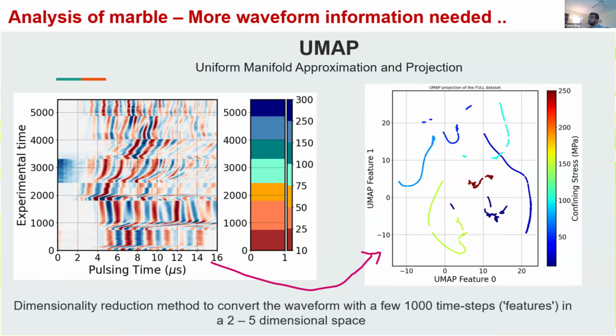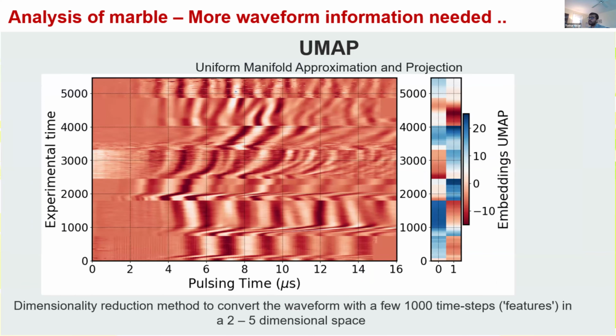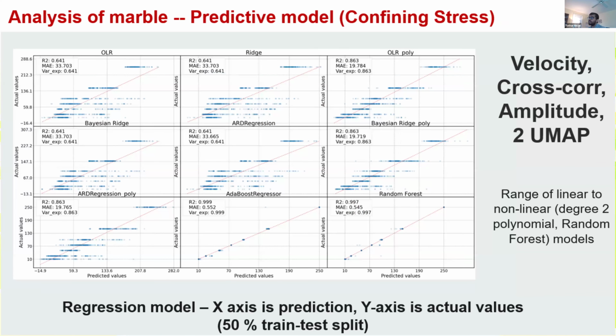So UMAP is not picking at any given aspect of the waveform. It's looking at all of the waveform together, but finding a very low dimensional representation that captures this information, with only 2 to 5 features, so you don't add hundreds of features to your data. So by doing UMAP, we can start looking at the effect of adding UMAP to the same type of tests that we did before. If we try to predict confining stress, where we have velocity, cross-correlation, amplitude, and 2 UMAP features, especially for the AdaBoost and random forest, we are getting almost perfect predictions.